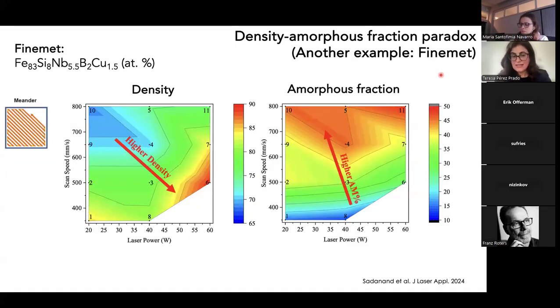This is just another slide, very similar to the previous one. This is just to show you that in the other commercial alloy that we were studying, this FineMet, which has a slightly different composition with niobium, boron, and copper, we obtained and measured exactly the same story. It could only be processed while retaining the shape in this very narrow, low power region.